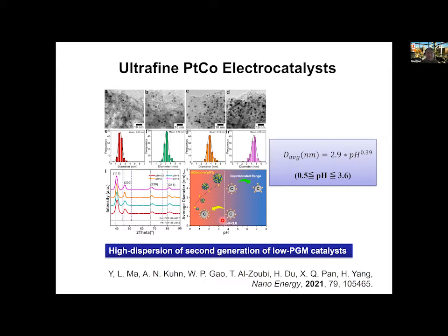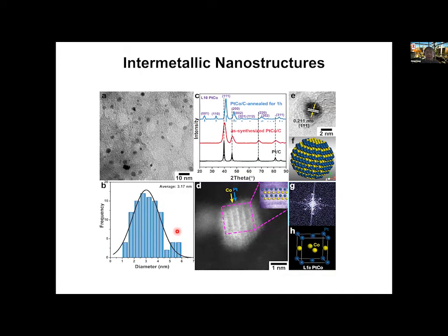And so these are the solution phase processing. That's a low temperature that allows us to get the precursor that eventually leads to the highly structured intermetallic. Indeed, after pyrolysis, the temperature treatment, roughly about 400 to 600 degrees temperature range, for about 1 hour, we'll be able to convert that into an intermetallic structure, as you can see from the signature XRD diffraction peaks,